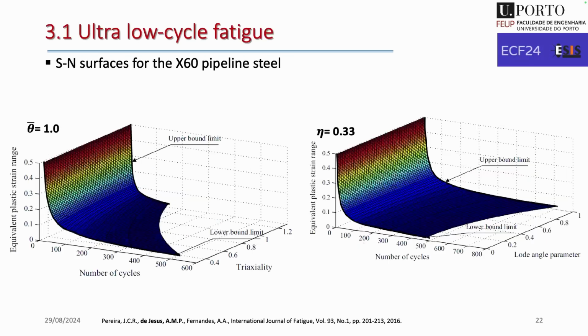With that, we can reach a new idea for the fatigue crack initiation in this fatigue regime, which is characterized by these surfaces. So we will have the S-N surfaces where we are adding an extra dimension, which will be triaxiality or Lode angle parameter. So we have a multi-dimensional surface for fatigue crack initiation characterization.